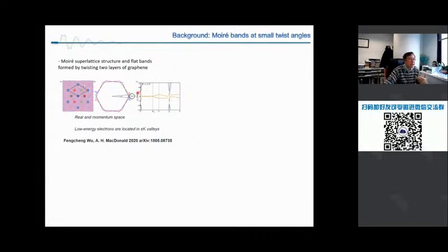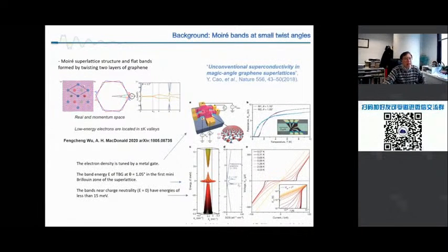So in momentum space, you will see small Brillouin zones. Okay? So theoretically, people calculate the band structures. In addition to the valleys that I demonstrated, there are more so-called flat bands, the mini bands. It's not perfectly flat, but it's called flat bands with a narrow gap. Right? So people make a device for the twisted structure and then calculate the band structure change and the density of states distributions around the Fermi level, once you change gating states at a certain filling.